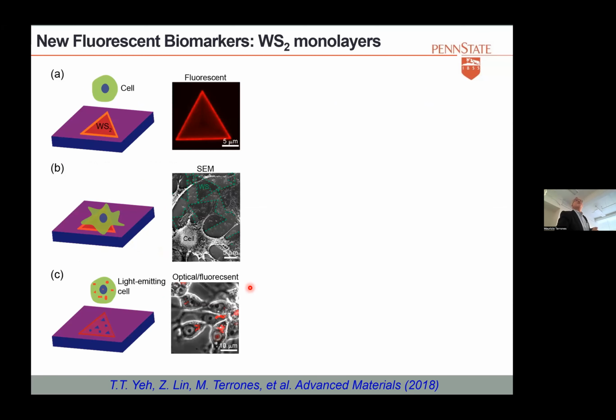And then we did some work on this. So basically, you grow your material, you put it on a substrate. In this case, we put it on a silicon quartz, sorry. And then you have the triangles here, and then you have the cells here. You put the cells on, and you can see the cells are on top of the triangles, and you can start to see the fluorescence after some time.